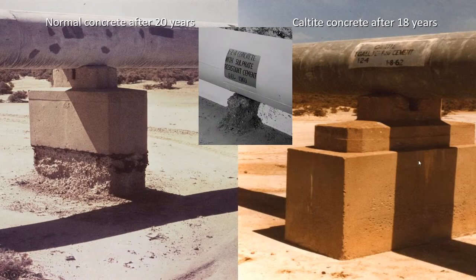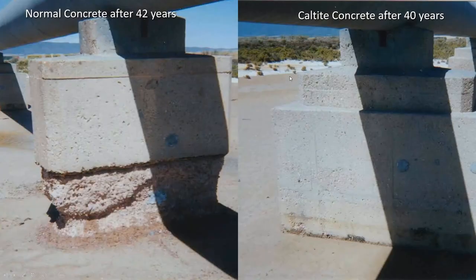This one, you can see actually salt water has spilled over the top and it's caused a stain here. And it's reinforced, remember, and there's not a sign of any corrosion, there's no sign of any sulfate attack. It's still a pretty good nick. It's got a few pot marks on it here, but that's eventually caused by windblown sand, so that's erosion rather than corrosion. Coming up, we've got after 40 years and 42 years, this was the last one standing of the unprotected chairs, and you can see the sulfate attack has got very bad and the salt scaling has got very bad.